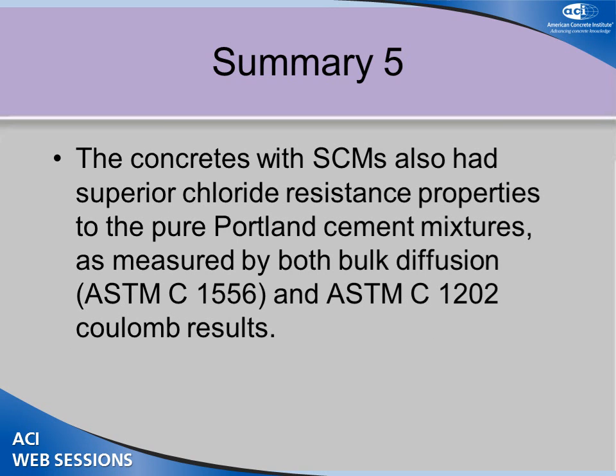I didn't show this data, but those SCM mixes, as you might have suspected, had much lower chloride diffusion coefficients, much lower Coulomb ratings than the Portland cement mixes. So the highway department, of course, wanted to use some of these mixes for bridge decks and highway structures where chloride ingress from de-icing salt is a concern to them. So that was what they're interested in as well. So, thank you for that.